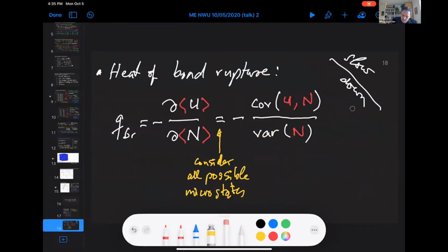So I marked myself here to slow down a little bit because I don't want to lose you, because now it becomes really interesting. This heat of bond rupture is the derivative of this energy U, which I have for each equilibrium state, with respect to N, the number of bonds that exist in the system. And now, because I have this Monte Carlo approach, this statistical physics approach, configurational mechanics, I created a lot of microstates, each one being defined by an energy U and a number of bonds. So I can statistically evaluate this heat of bond rupture.